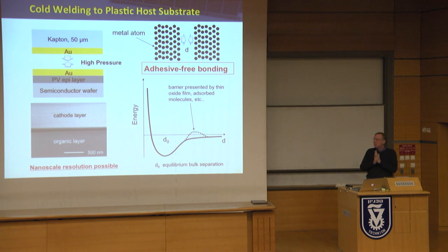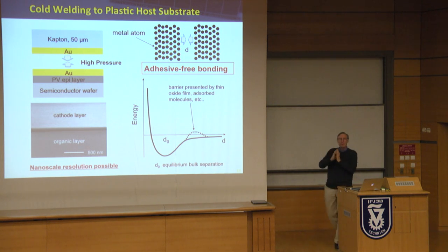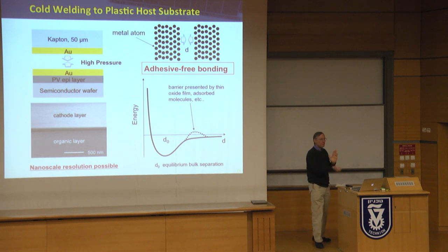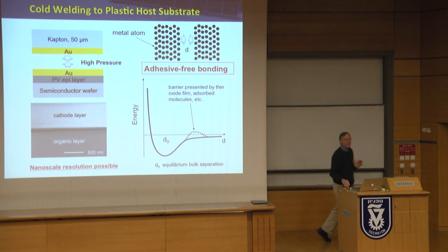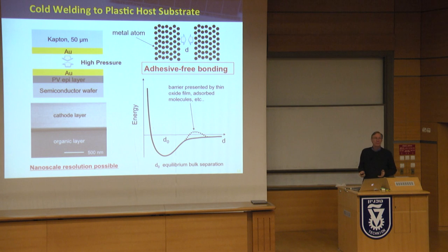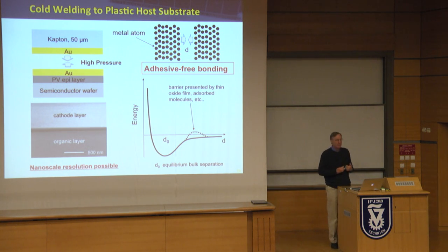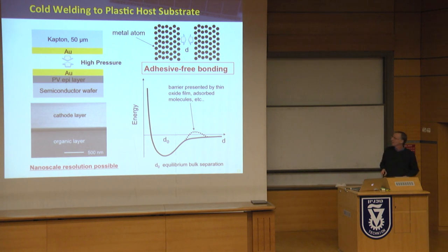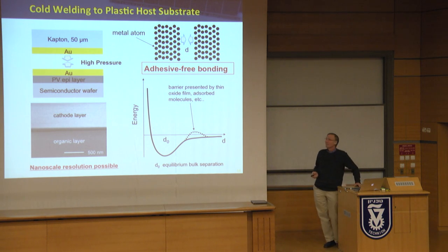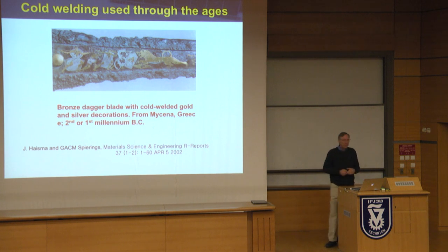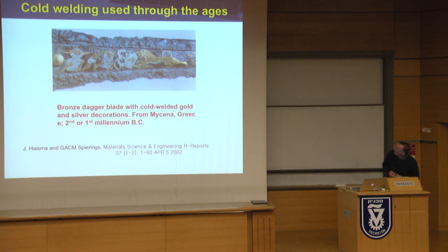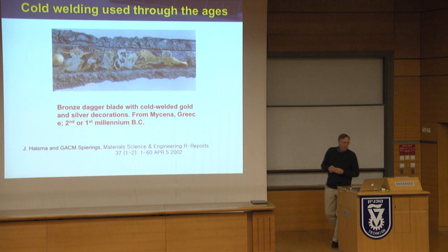And then there's this so-called avalanche, and that avalanche means that the electron system all of a sudden gets shared between the two surfaces, and it forgets there was ever a difference. And so this is much stronger than any adhesive you can ever put on. As a matter of fact, it just looks like a thicker layer of gold, which is ideal for flexibility and for durability. Well, we thought we were pretty smart, but then we learned that we were beat.